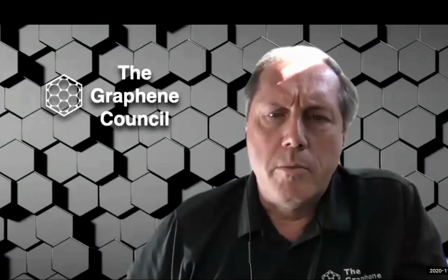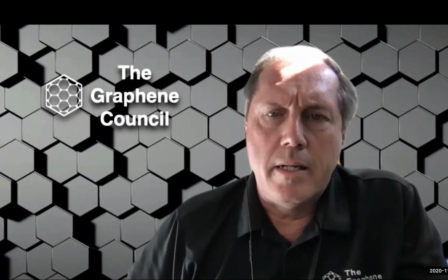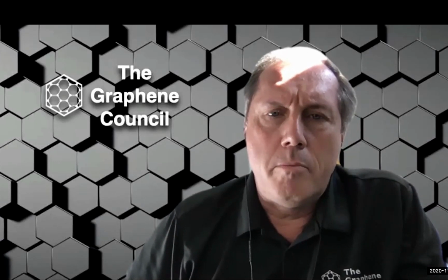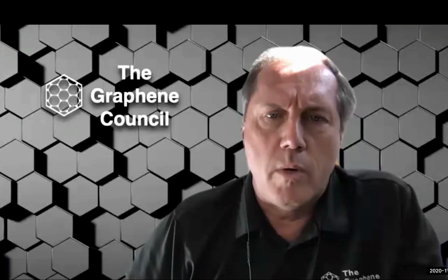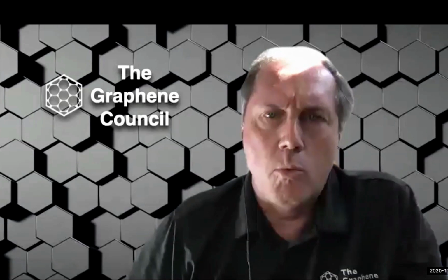And if you don't mind, I'll jump in just for a second. I mentioned before we're doing a composites head-to-head testing project. That material is being compounded by one of our partner companies, ChromaFlow, who is doing the dispersion. Part of the magic of getting graphene to work is in the dispersion process, which is an acquired skill. It depends a lot on the morphology of the particular material. So we recommend that companies who want to use graphene enhanced resins don't handle the graphene material itself, but work with a compounder or someone who has experience in dispersing the material.